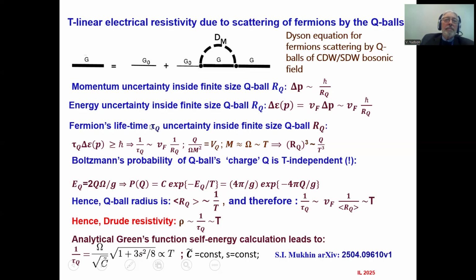Now, if we consider the lifetime of the electron in this state when it goes through the Q-ball, then we have the Heisenberg inequality that lifetime times uncertainty of energy is greater than h bar, and then we get this relation that 1 over tau_Q is proportional to v Fermi times 1 divided by the radius of the Q-ball. And now when we look at this relation for the Q charge, which is temperature independent, when we divide by omega m squared, and indeed m is proportional to temperature, then omega m squared is proportional to the cube of the temperature. It means that the volume is inversely proportional to the cube of the temperature, so the radius is inversely proportional to temperature. And that's how you get this 1 over tau_Q proportional to 1 over R_Q.